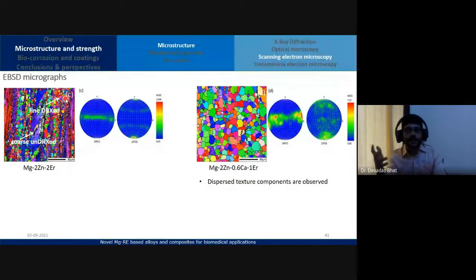You can see here that for this particular alloy, we could see certain DRX, that is, dynamically recrystallized grains, which are fine in size, and then we also have some coarse grains which are not dynamically recrystallized. So these are partially or not recrystallized grains. Now they have a very dominant prismatic texture, and that's the reason why you could see that the overall microstructure exhibits that texture. For the other alloy also, we see that the textural components are dispersed.